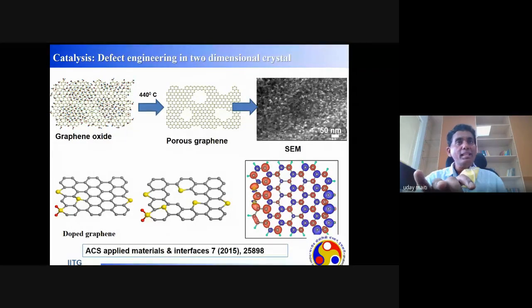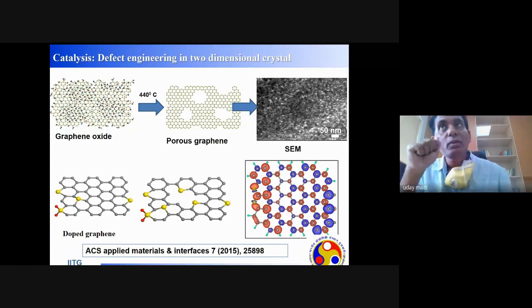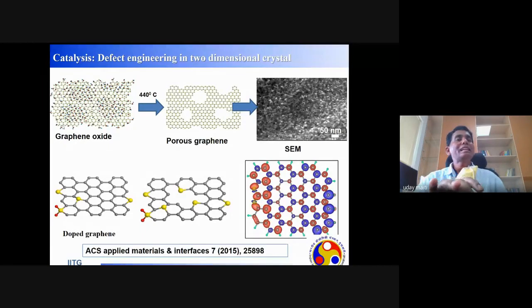And there is also some patch here. This is functionalized. So this is a percolated network of graphene and functionalized graphene. Now we took this as important information, that because it has two percolated regions, if we heat the graphene oxide, we can expect the two different regions, due to their two different chemical structures, to have two different burning points. So we controlled the temperature, 440 degrees Celsius, and found that those functionalized regions, the most disordered regions, burn first. As a result, we can create some holes within the graphene plane.